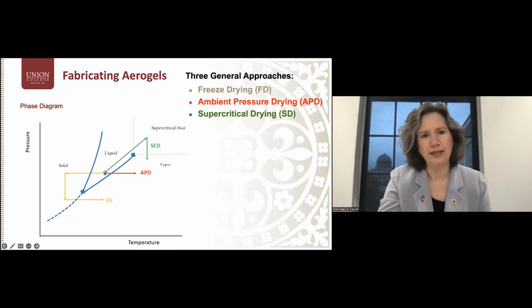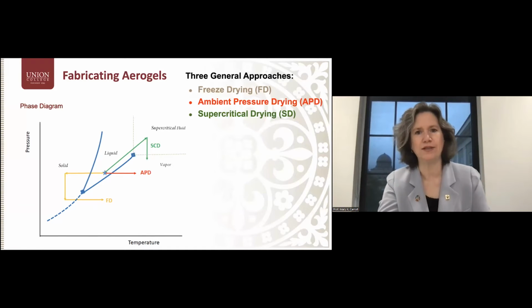Another possibility is to cool down the mixture, drop both the temperature and then the pressure, and freeze dry it. And this method allows you to make generally powdered aerogel materials. They generally don't stay as an intact monolithic species.